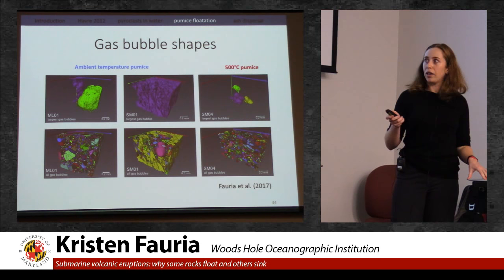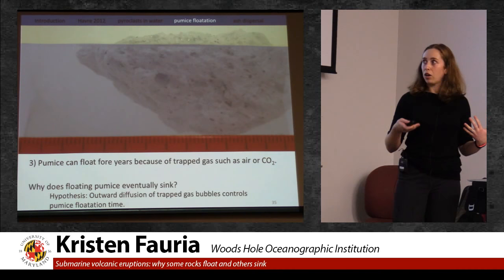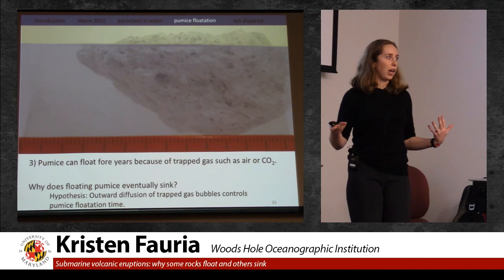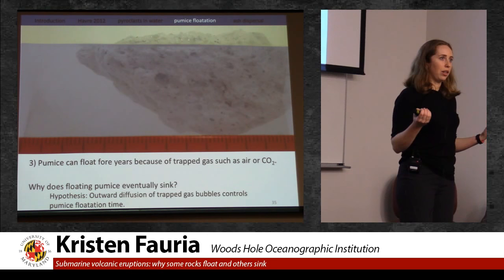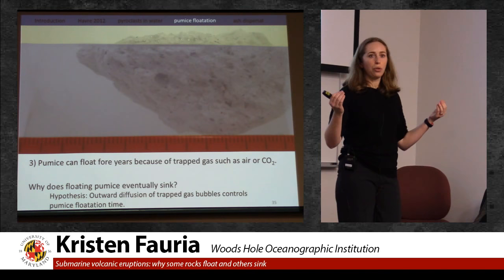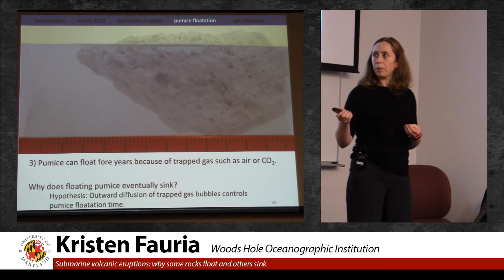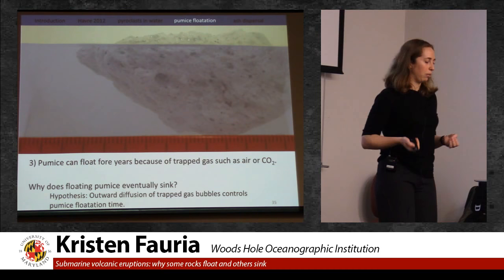But eventually, the pumice doesn't float forever. It eventually either grinds down, washes ashore, or is able to sink to the bottom of the ocean. And so what is it that allows the pumice to eventually sink? Our hypothesis is that these isolated gas bubbles that are surrounded by water can diffuse through the liquid water and eventually to larger bubbles and eventually out to the atmosphere. So we think that it's the diffusion of these trapped gas bubbles that eventually limits the pumice flotation time.